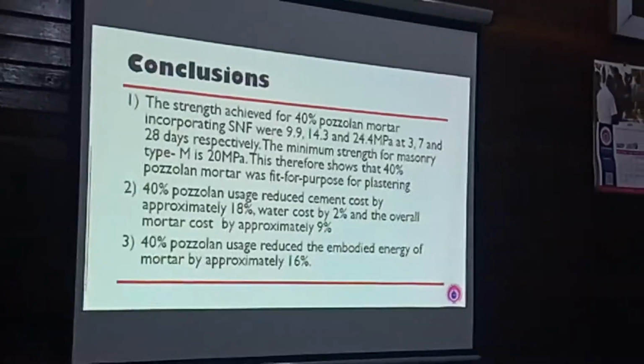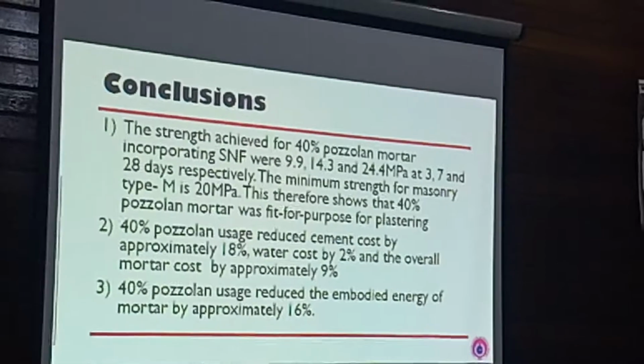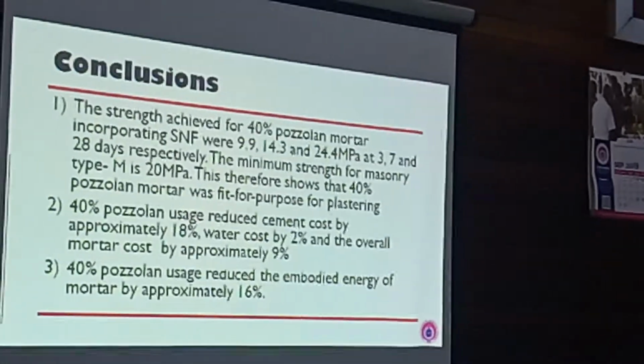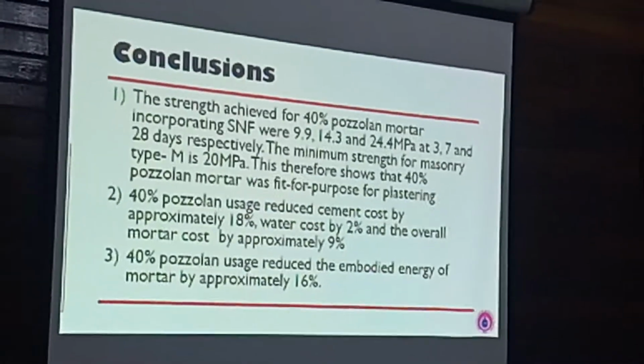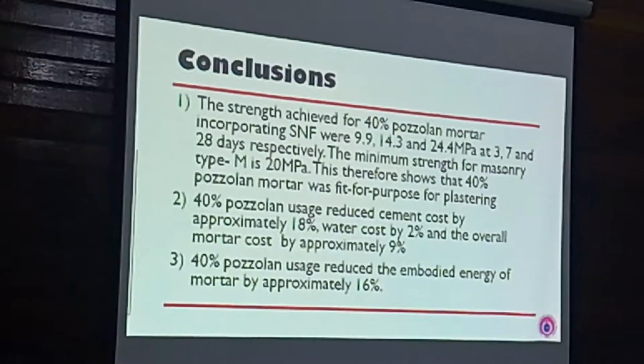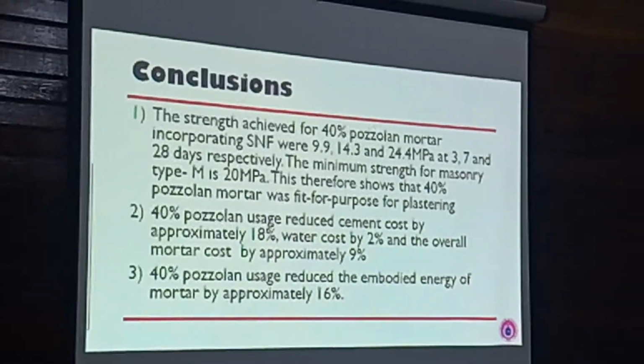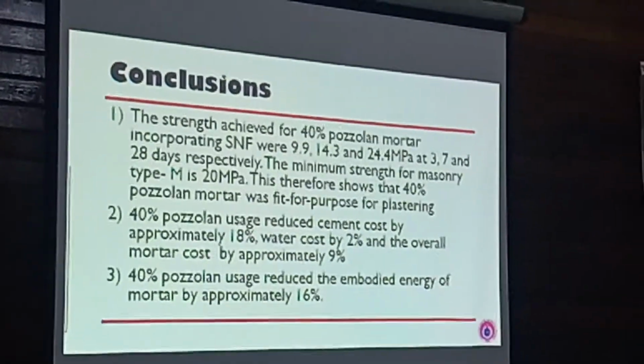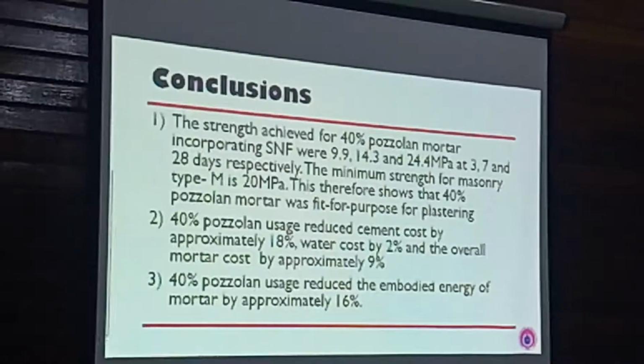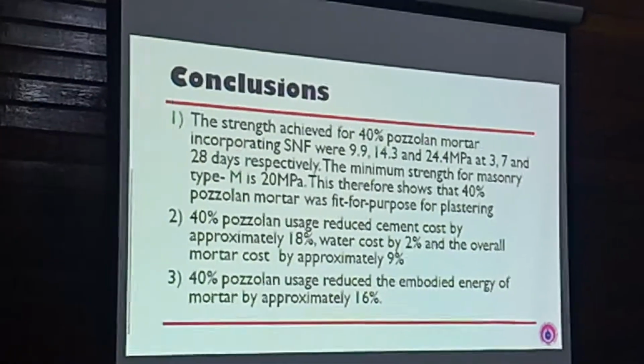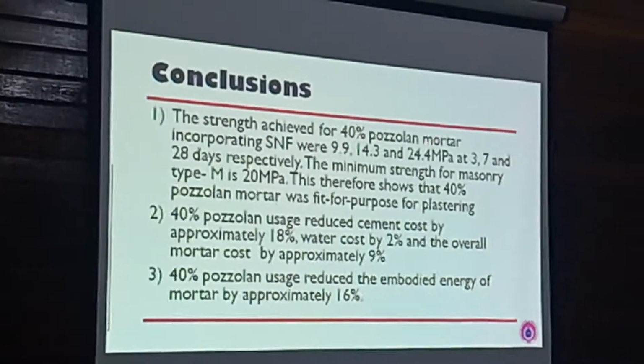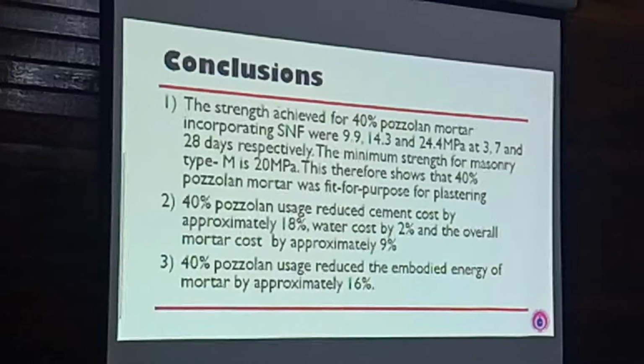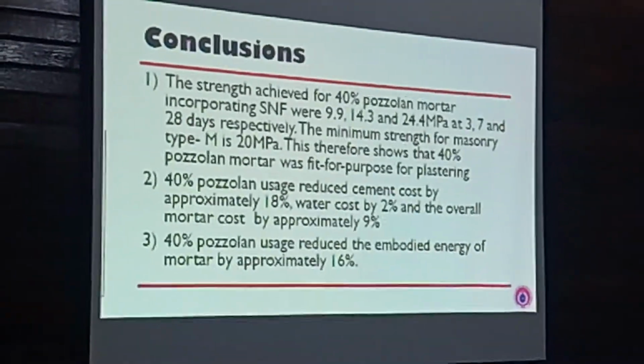Well, let me try to conclude. After walking you through all these things, embodied energy, cost analysis, strength, and all the practical experience that I did, these were some of the things that we can conclude on. At 40%, when you incorporate the SNF, the sulfonated naphthalene formaldehyde, the compressive strength that we achieved at 3, 7, and 28 days were 9.9, 14.3, and 24.4 megapascals. Of course, when you compare it to the standard, it is higher than the standard, so you can use it. Because before the standard comes out, they have tried and settled with their value of 20. So there is nothing to repeat.